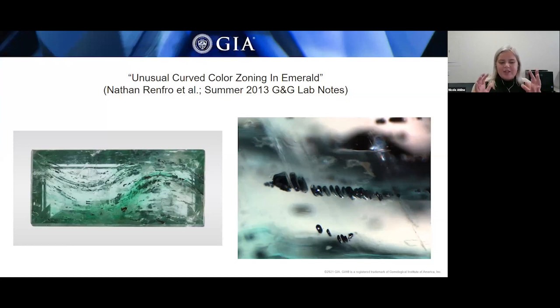But that S-shaped green color zone throughout it was just highly unusual, considering emeralds generally have more of a planar or angular color zoning that is related to the crystal's morphology. One possible explanation is that compressed geological forces cause shearing along the emerald crystal's basal plane. In the photomicrograph on the right, you can see these pyrite fragments, and they support this idea. This appears to be one single pyrite crystal that has been sheared and then slightly misplaced by a lateral shearing movement throughout the emerald.